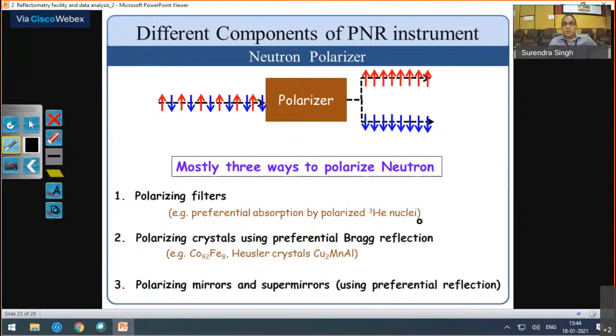See, the neutron absorption and scattering depends on the, because it is sections. So if you polarize the helium, one of the spin gets absorbed, and that principle is used here to get a polarizing filter. So one of the spin, if you polarize the helium nuclei, one of the spin absorbs and only another spin goes away. So that will give you the polarizing.